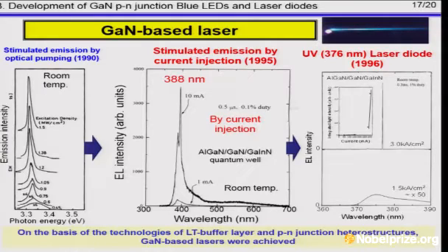In the 1990s, we achieved the stimulated emission in the ultraviolet region at room temperature for the first time, with 1 order of magnitude lower optical power than before, from the high quality gallium nitride. And in 95, first stimulated emission by electric current injection using high quality quantum well devices. And also, we developed in 96 nitride-based laser diodes and also the ultraviolet laser diode.